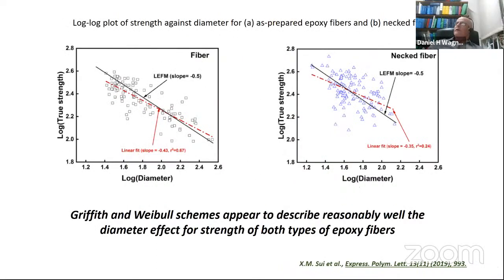So now we conclude using our data that the Griffith and the Weibull scheme both appear to describe reasonably well the diameter dependence of the strength of both types of epoxy fibers. You see the slope is 1/2 for the LEFM, and there is quite a lot of spread in there, especially for the necked fiber, but the slope is still going through in a reasonable way for the fiber.